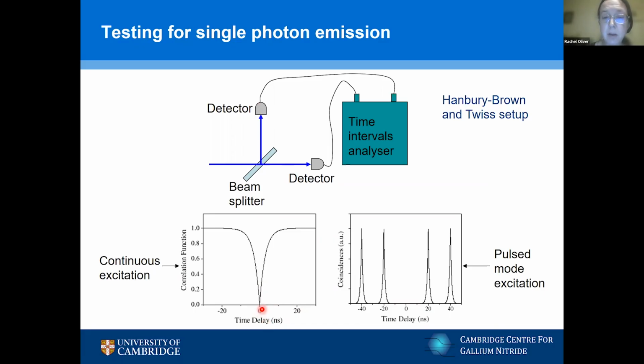But we could have a photon arrive at one detector and then 20 nanoseconds later arrive at the other detector. Or we could have a photon arrive at one detector and then 20 nanoseconds earlier there have been a photon at the other detector. That would all be fine for a single photon stream. This is what we see for continuous excitation of our single photon emitter. But a lot of the experiments I'll show you today use pulse mode excitation. So essentially, we're like pressing the button and requesting a photon every 20 nanoseconds.